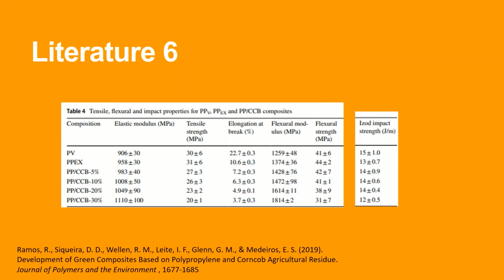However, addition of corncob particles increased the elastic modulus of the composites, significantly at higher particle loading, around 10 up to 30 weight%, and was said to be caused by the stiffness of the woody ring that is similar to the composites made from wood and plastic. Different flexural properties were observed from composites with varying amounts of corncob content.